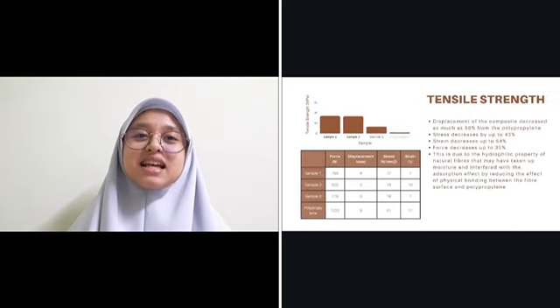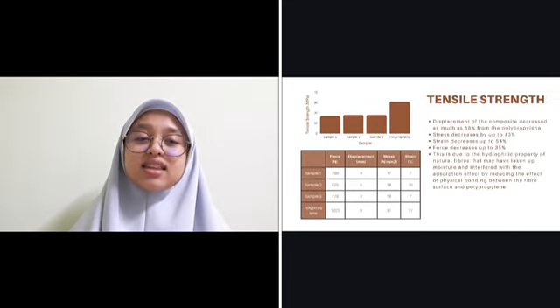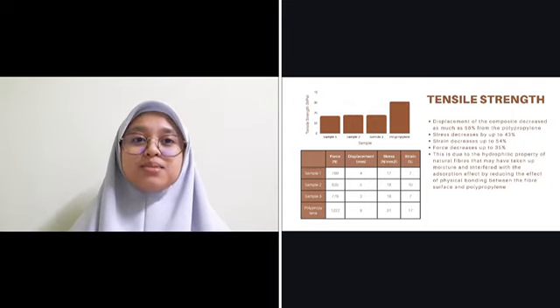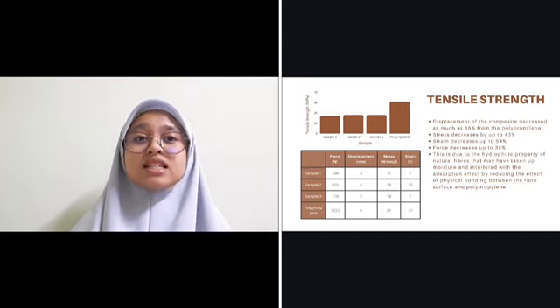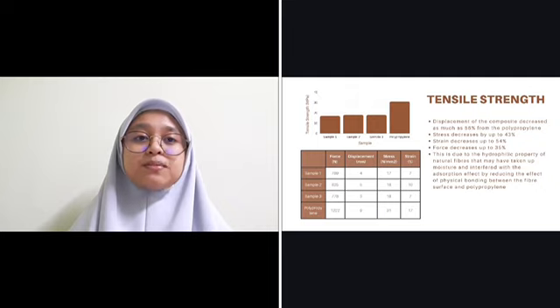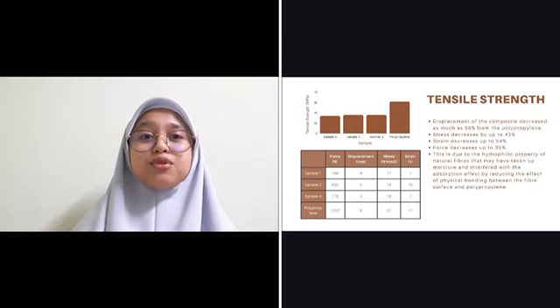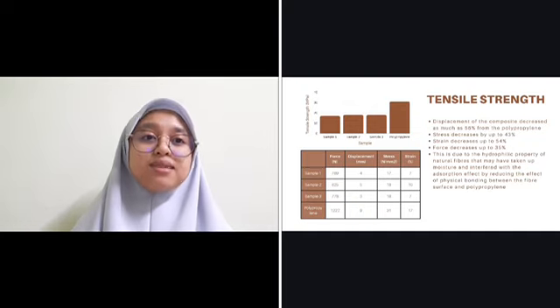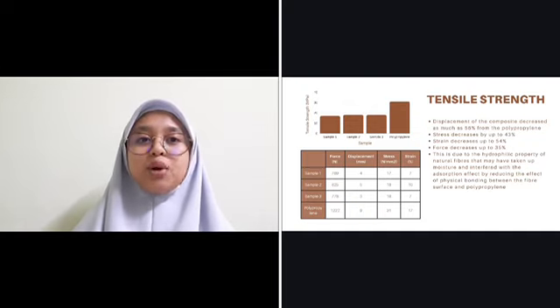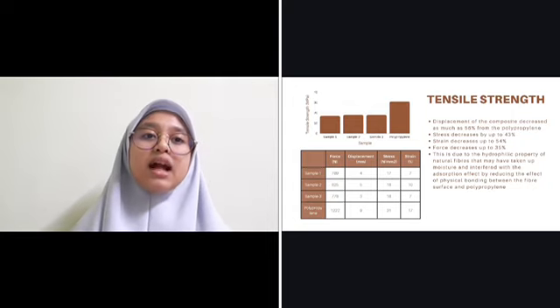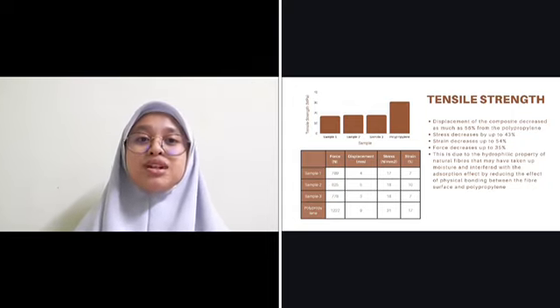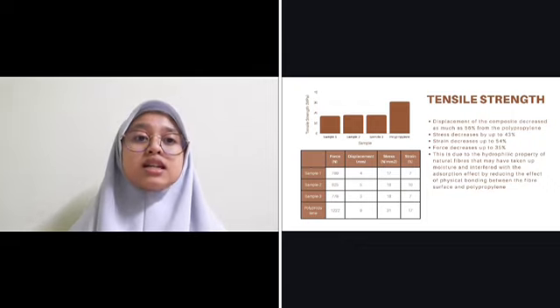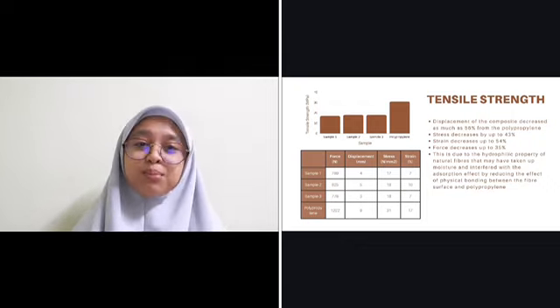The next test was the tensile strength test. The tensile strength test of EFB reinforced polypropylene composite showed that the displacement of the composite decreased as much as 56% from the polypropylene. The stress decreased by up to 43%. The strain also decreased up to 54%. At the same time, the force decreased up to 35%. This is due to the hydrophilic property of natural fiber that may have taken up moisture and interfered with the adsorption effect by reducing the effect of physical bonding between the fiber surface and polypropylene.